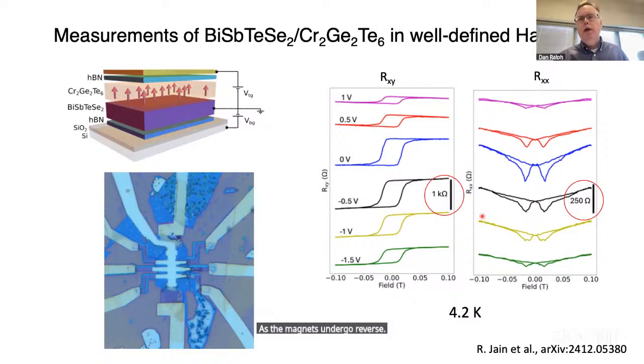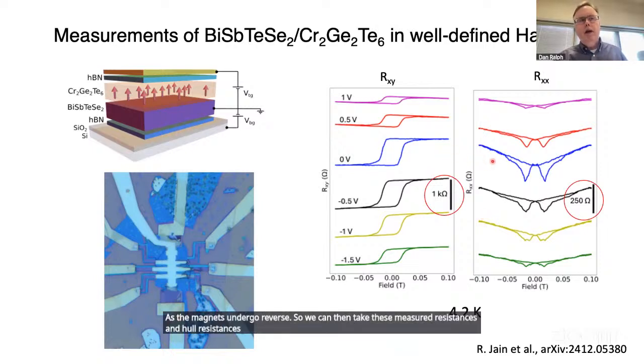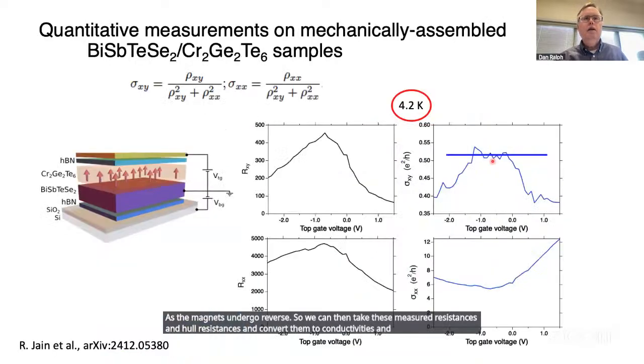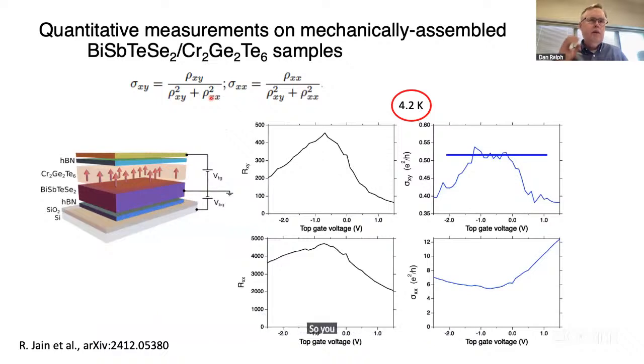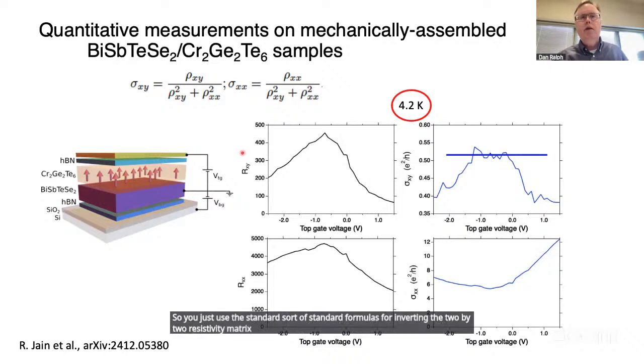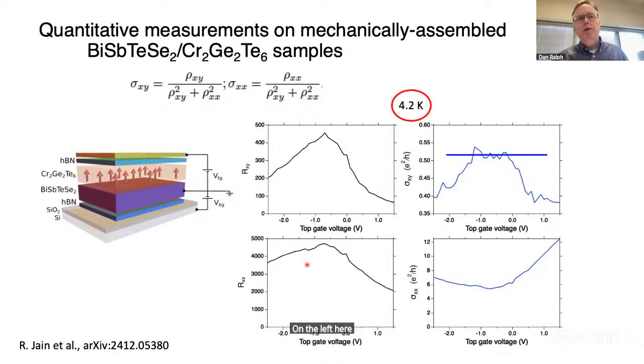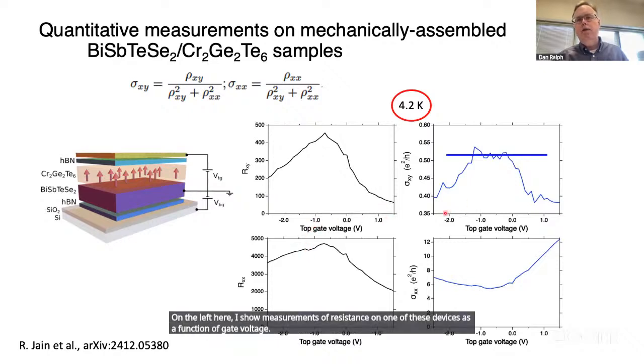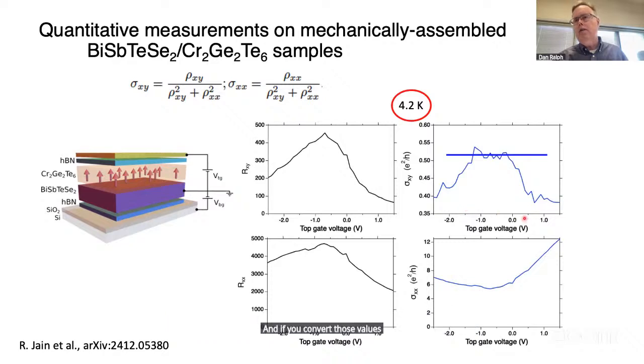Okay, so we can then take these measured resistances and Hall resistances and convert them to conductivities and see what we see. So you just use the standard formulas for inverting the 2x2 resistivity matrix to determine conductivities. On the left here, I show measurements of resistance on one of these devices as a function of gate voltage. And if you convert those values to conductivities, what you see is on the right.